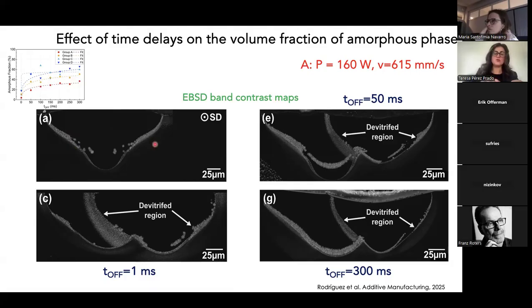And then what we did was to melt a second, neighboring pass, with different time delays. One, the default value, this is here, then here 50, and then 300. That's what you can see here. So, of course, if we don't use any time delay, the default value, this is the second melt pool. And what was just after the first pass amorphous phase becomes crystallized. There is the devitrification of the previously deposited amorphous phase, and all this region here is crystallized, formed during the heat-affected zone of the second pass.